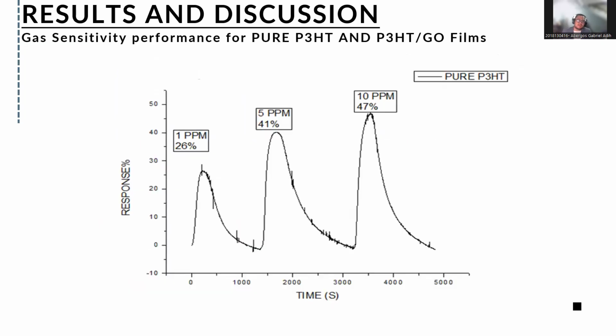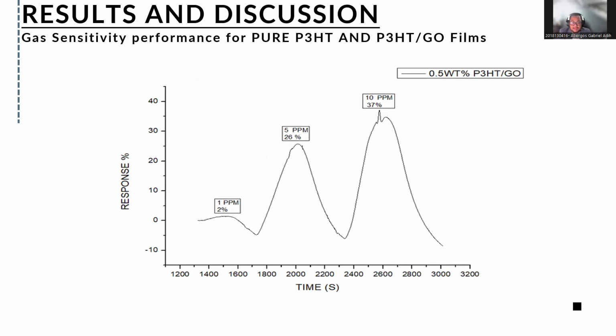So here's the application. We start with the gas sensitivity performance of pure P3HT. At 1 ppm, we see a 26% response, then 5 ppm at 41%, then 10 ppm at 47%. This means that P3HT responds to gas levels which increase in concentration. But as we can see for 0.5 weight%, it is slightly lower at 1 ppm, only about 2%, but it increases at 5 ppm to 26%, then 10 ppm at 37%. This shows that adding a small amount of GO reduces the initial sensitivity of the composite. This is due to the changes of the charges and interaction of the surfaces.